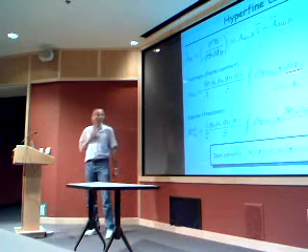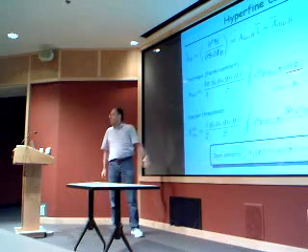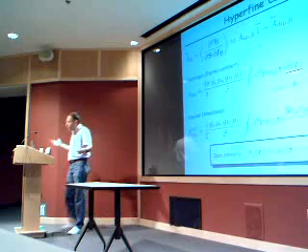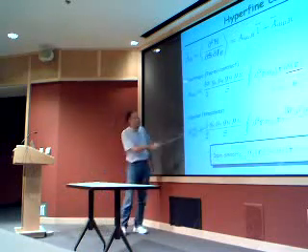And this is very important to study electronic structure, because remember that only the s orbitals have a finite density on the nuclei. P and d orbitals have nodes on the nuclei, right? So basically, the Fermi contact term can tell you how much s wave function you have in your system. So it can give you basically the hybridization of your system.